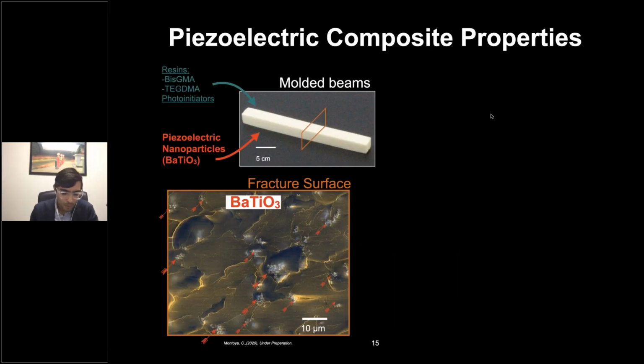To show that, what we did first was make our own resin. We combined a typical BisGMA, TEGDMA resin, and added nanofillers of BTO, a known biocompatible piezoelectric nanofiller. We went to the microscope, broke the sample, and checked all of the nanofillers that were in place, that they were evenly distributed.